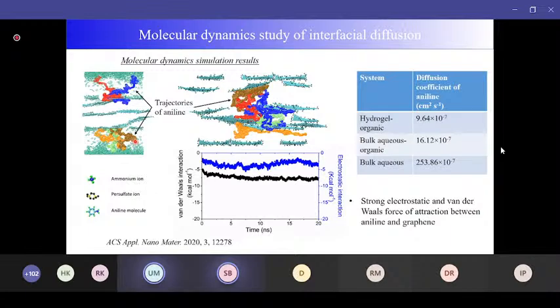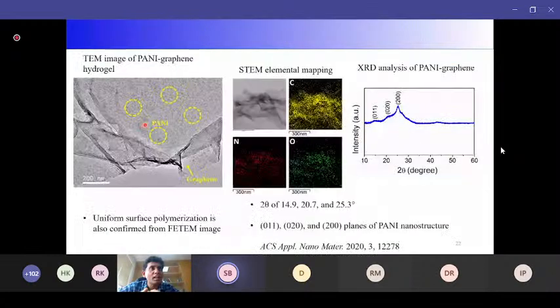So this slow feeding of the reactant into the hydrogel gives rise to this uniform structure, which we expected and have found from our molecular dynamics simulations also. And as you can see from the TEM image, right now you cannot see any nanowire structures of the polyaniline, so there is a uniform coating of the polyaniline over these graphene sheets, and there is a uniform distribution of carbon and nitrogen, which also signifies that the polyaniline uniformly covers the surface, and XRD analysis also confirms that this particular material is polyaniline.